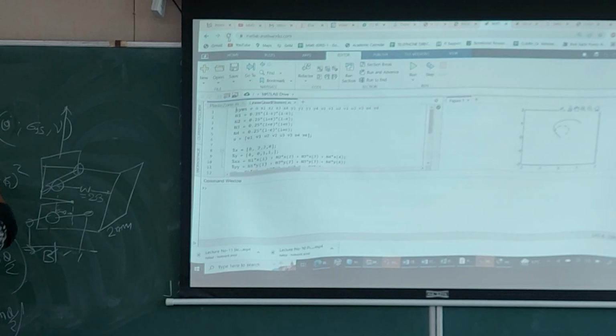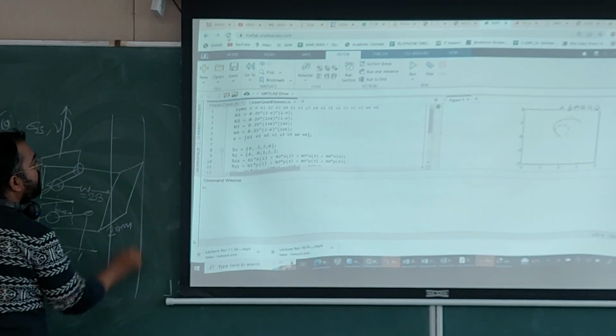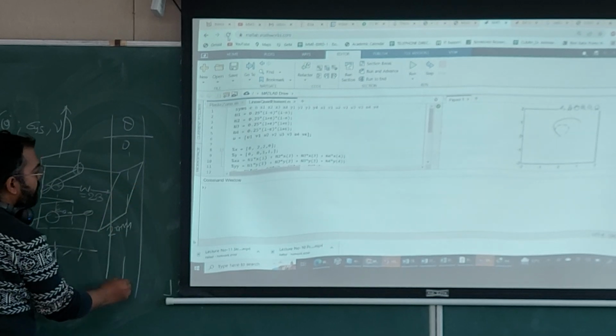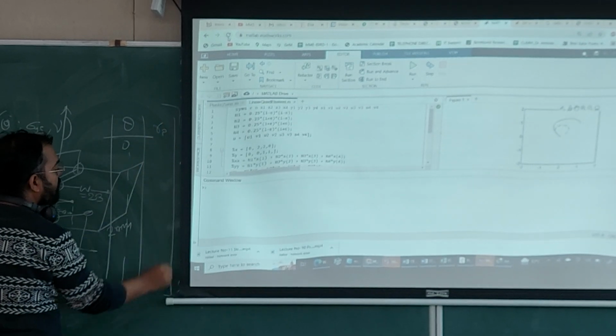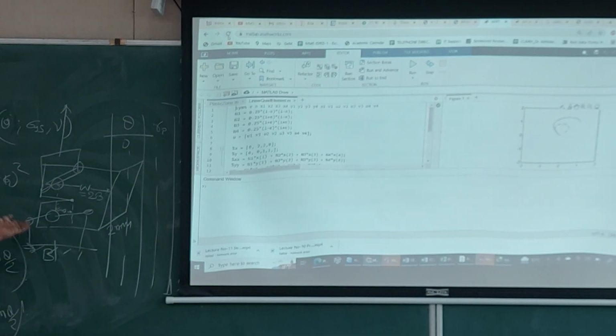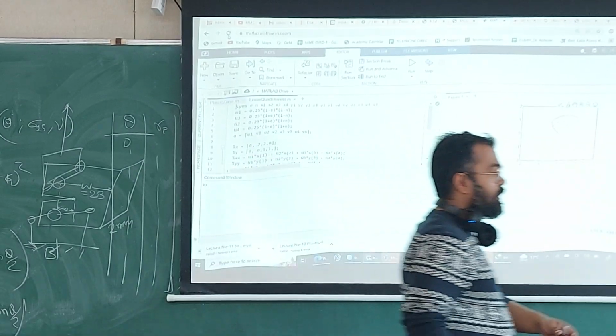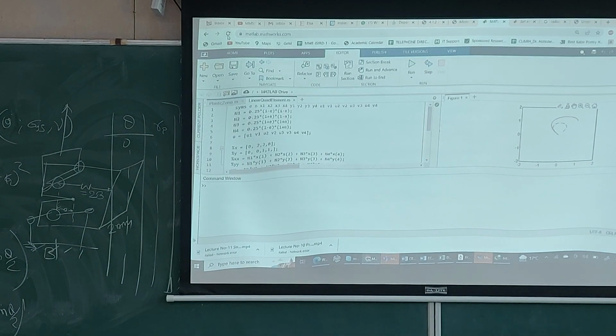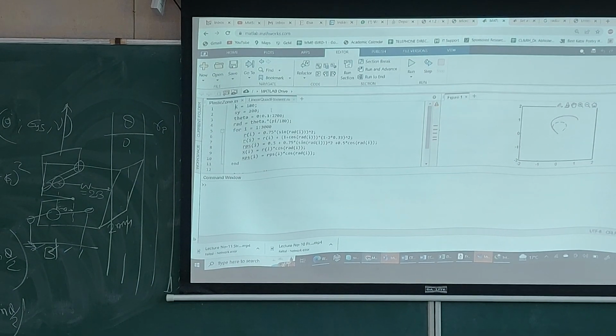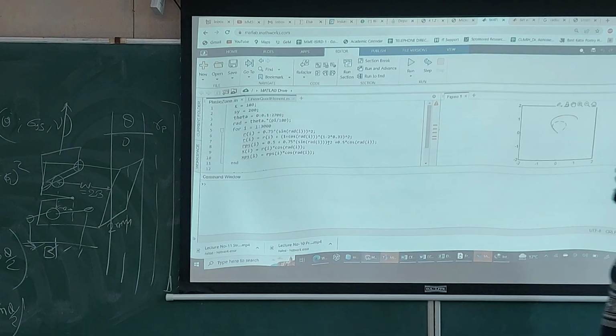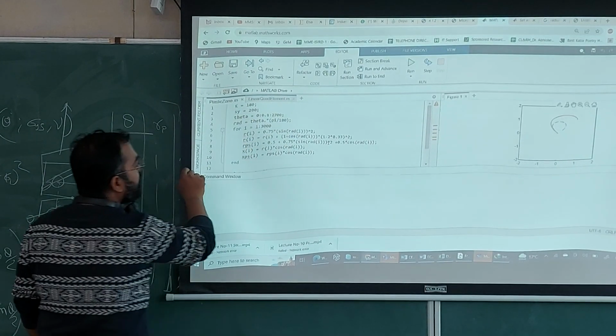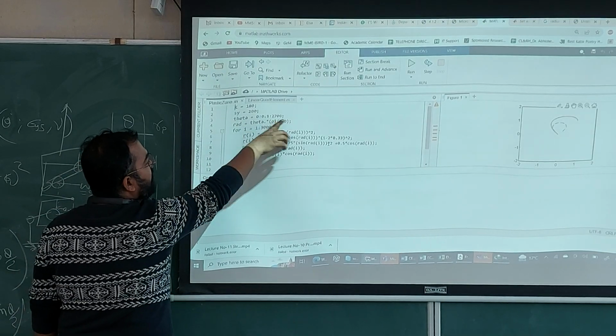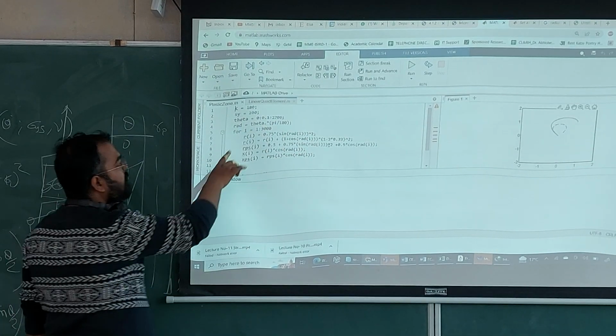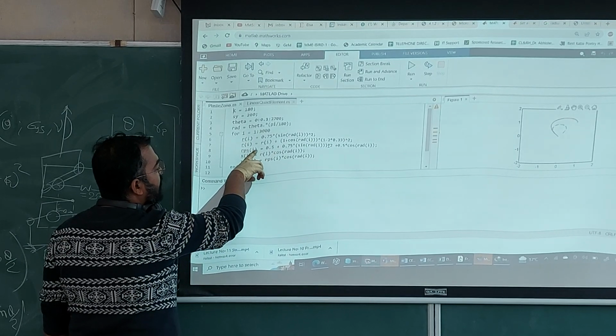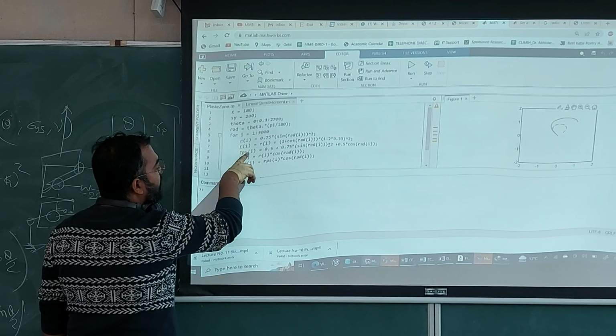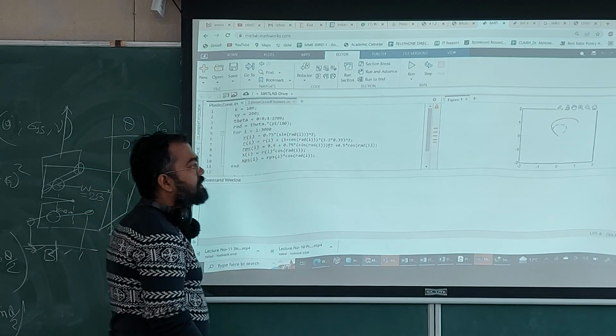So for different values of theta in MATLAB, you can have theta going from 0 to whatever. You can calculate the r value, and then you plot r versus x, or normalized r versus x. So that's what I have done for you guys. Do you see here? Some arbitrary value of k and sigma y, and then theta is varying from 0 to 360, and then you calculate the value of plastic zone radius for plane stress condition and for plane strain condition, and then you plot it.